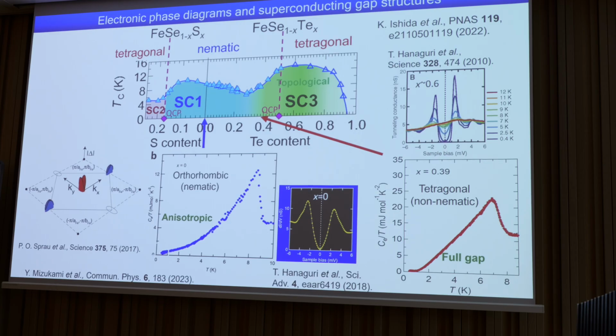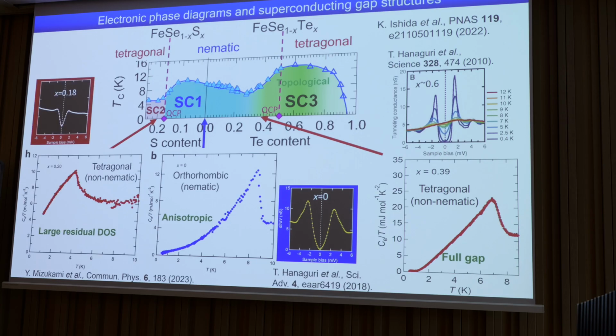If you go to the SC2 side, this was a very surprise because C over T looked completely different. You find a very large residual density of states in the C over T at low temperatures. And if you look at the tunneling data, you actually see a significant zero bias conductance, which is consistent with the specific heat.